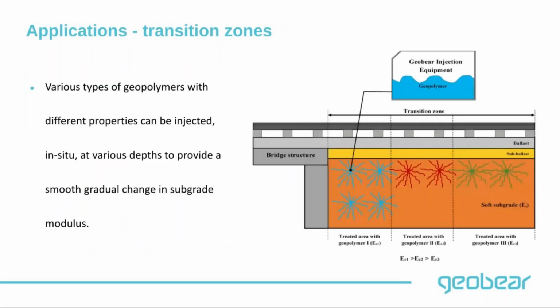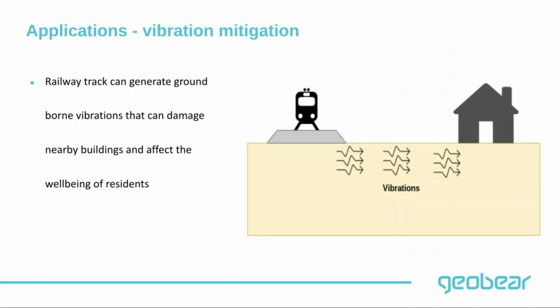Okay. So what can we do with this? Well, we can actually inject the material. We can inject the material in such a way that we create transition zones. So we inject at different depths with different materials, so you reinforce the subgrade stiffness gradually. So as you get to the bridge, you've almost smoothed out your transition. That's a very effective way of doing it, and that would not involve any excavation or taking out the track or anything. So that's an in situ treatment to the problem.